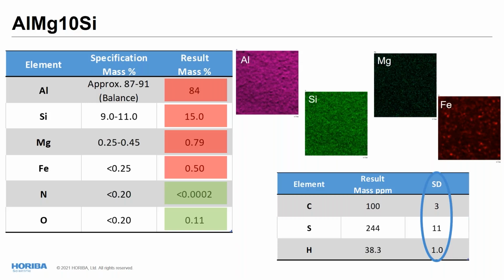Then this analysis was performed with 2 different techniques, several instruments, but overall, in a few minutes, we were able to show that the powder should not be introduced in the process, and that really helps to identify issues before starting the process, rather than waiting for the final part to be tested, and most likely in this case, to fail